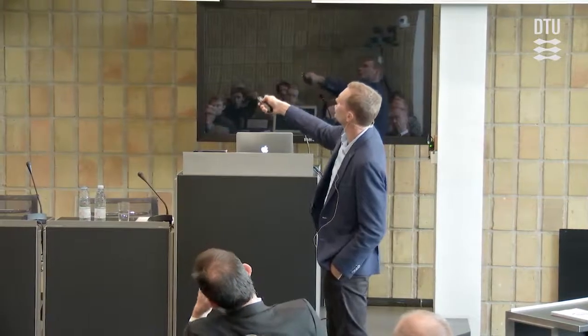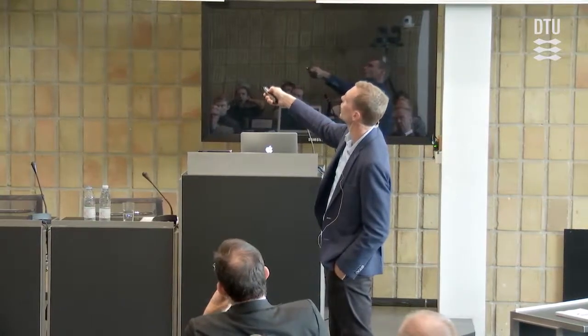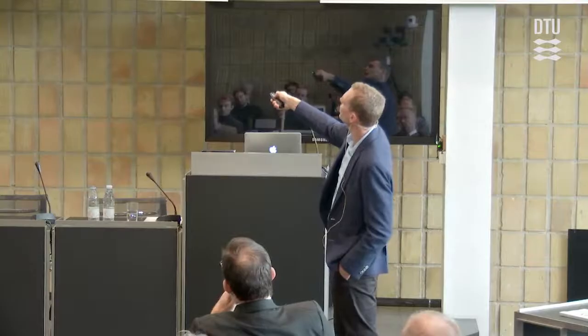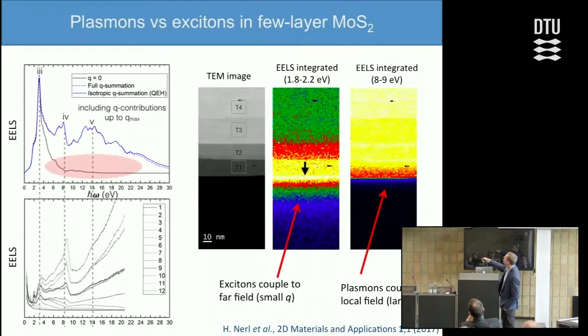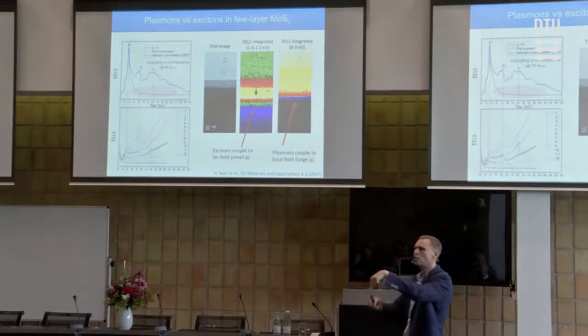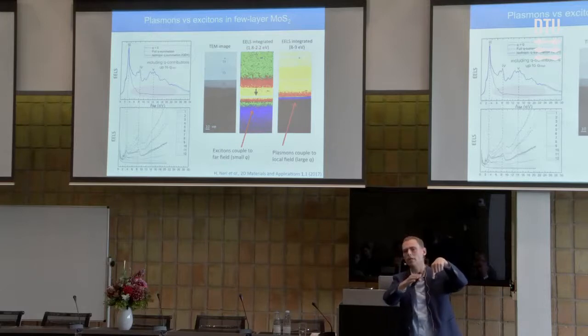This is the spatial EELS spectrum integrated over the range of the excitons, and you can see this is where the border of the sample is. In this regime, the electron beam is actually parked outside the sample, and still there is a lot of signal. That's because the electron beam has a slowly decaying tail—the small Q values of the electron beam exciting the excitons.